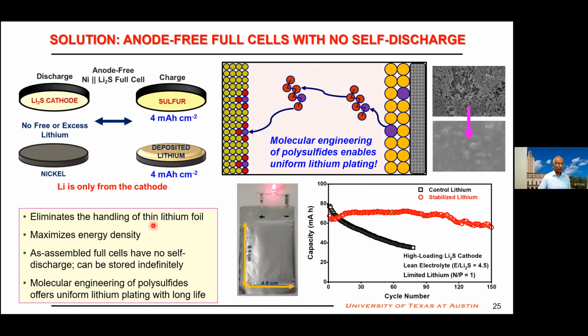Handling lithium metal foil is not easy either. How are we going to make thin lithium foil? How are we going to handle all that? Those are problems. We eliminate that. It maximizes the energy density because you do not have to have free lithium. And as-assembled cells will not have any self-discharge. And then finally, we have to do some molecular engineering with the polysulfides to overcome the lithium metal stabilization.